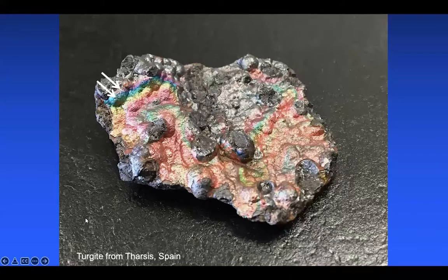And so we became convinced that indeed it was these void layers that were serving as reflectors and are responsible for this iridescence that we see in this spectacularly colored turgite. So here's a specimen from my own collection from Tharsis, Spain. And we decided, let's take some thin sections from two adjacent colored bands. As you can see arrowed here, we have a violet band close to a blue-green band.